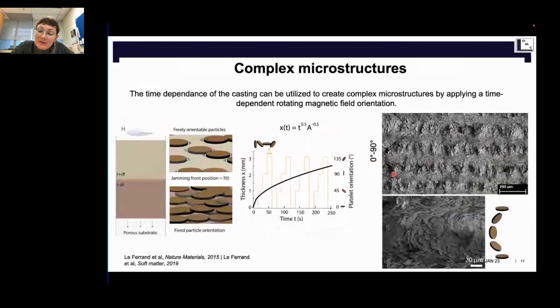And we can make even more complex microstructures if we modify the orientation of the magnet as the sample is dried. So basically, as long as the sample is a little bit wet and as long as the platelets have space to move, they will be able to align with your magnetic field. Once it is dried or once it's too concentrated, then they will get stuck in their orientation. So this is what we applied to create this kind of 0-90 periodic orientations or to smoothly vary the tilting of the platelets.